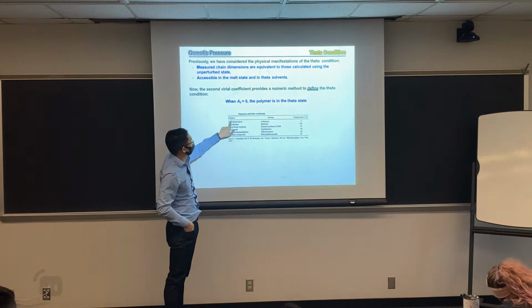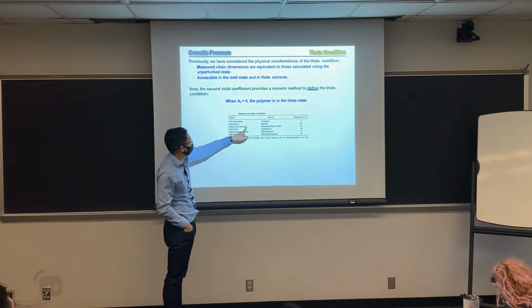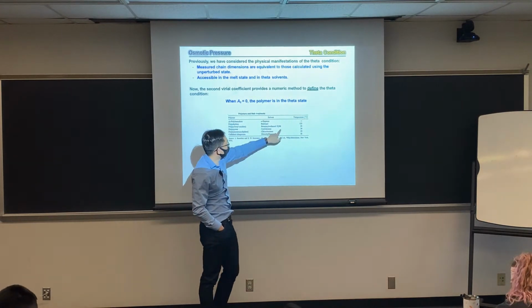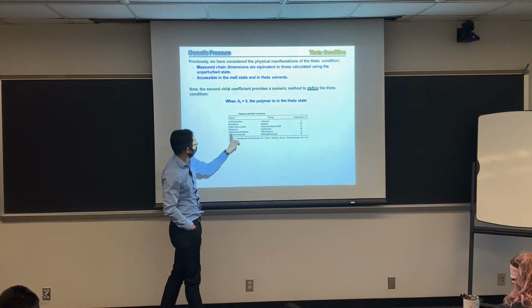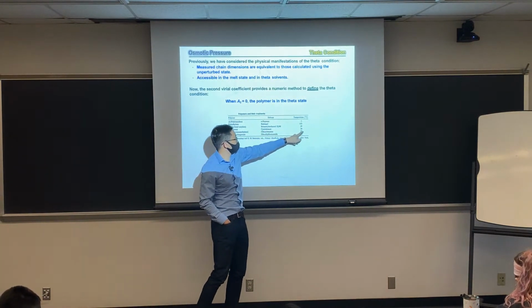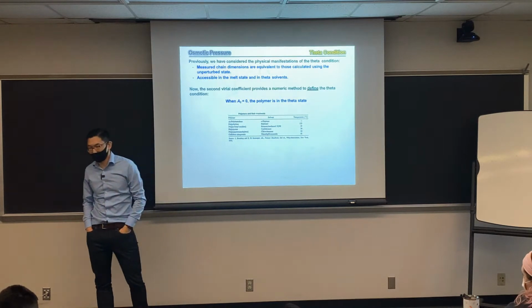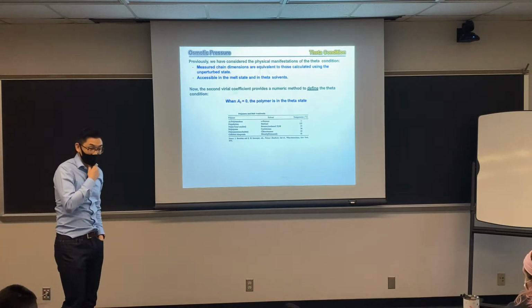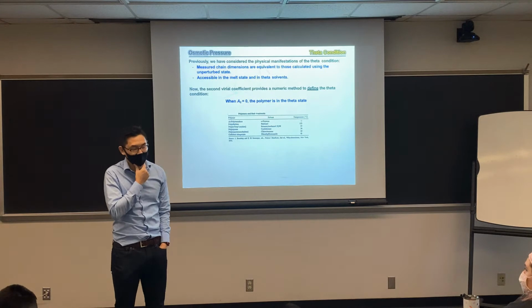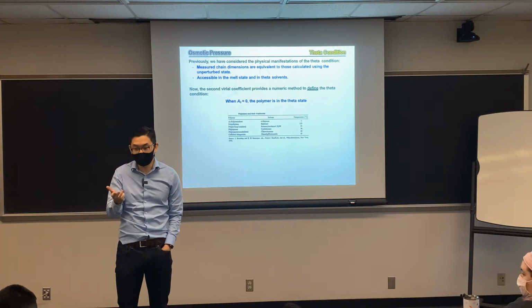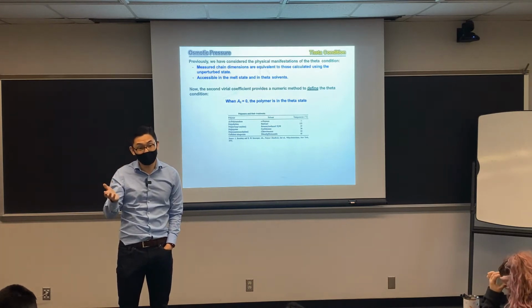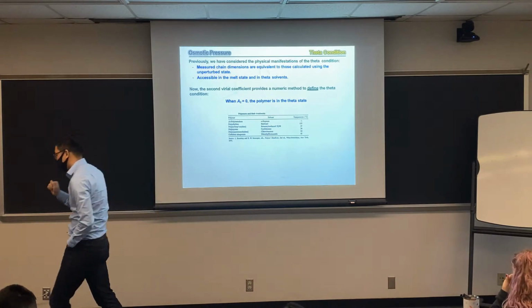Here is an example of several polymers with their theta solvent and theta temperature. For example, polyethylene in biphenyl at a relatively high temperature, or polystyrene in cyclohexane at 33 degrees, is a good example. It gives us the ability to do polymer physics experiments at the theta condition to test our theories. In reality, you can find the theta solvent by osmotic pressure.